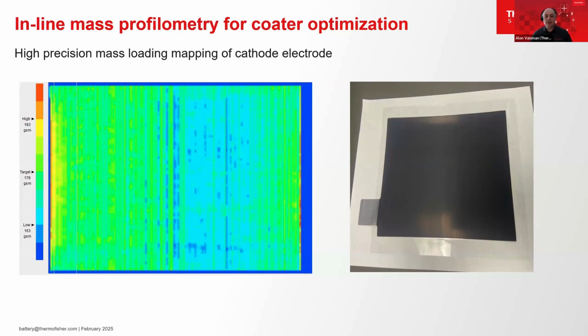In addition, one should consider the value of reducing the amount and cost of scrap that is produced during startup activities and the initial process qualification. In the example here, the operator makes a change to the process to correct the low loading region, but in doing so, they create a problem on the edges of the patch where the loading becomes too high. Without an in-process analyzer capable of detecting these variations, the user would have to rely on laboratory sample tests that can take many hours and result in production of a large amount of out-of-spec material.